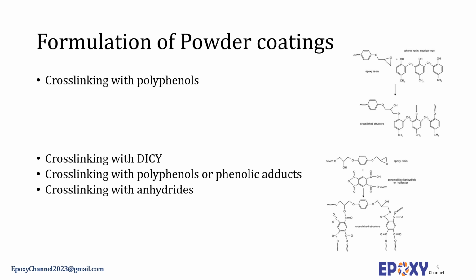During the cross-linking, the NH groups of these curatives react with the epoxide rings of epoxy resins by addition reaction. Dicy contains 4 H atoms attached to different N atoms, but its effective cross-linking functionality is lower. However, Dicy catalyzes the self-cross-linking reactivity of epoxy resins in a way, and therefore less than the calculated stoichiometric amount of Dicy is often required for cross-linking. Practically, a 97 to 3 or 95 to 5 ratio of epoxy resins and Dicy is always used.